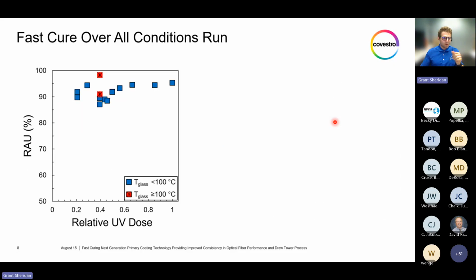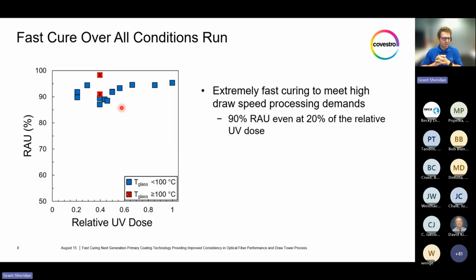Next, I'm showing the degree of cure of these coatings versus the relative UV dose, and have split it to show the glass fiber temperatures below 100 degrees C in blue and those above 100 degrees C in red. So as we can see, this next generation coating cures extremely fast as well, on an actual draw tower, to meet the high draw speed processing demands in industry. We were able to achieve 90% degree of cure even at only 20% of the maximum UV dose.